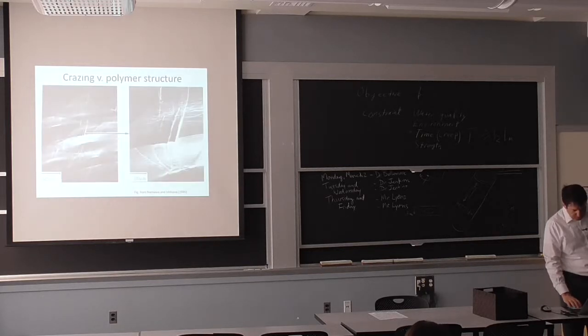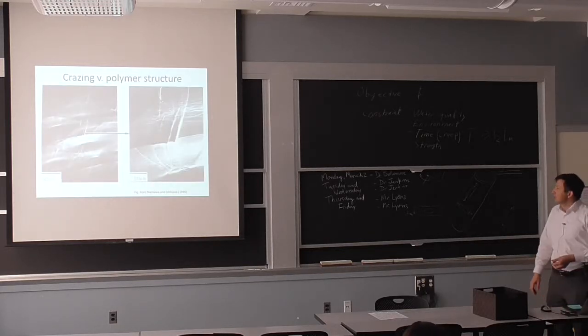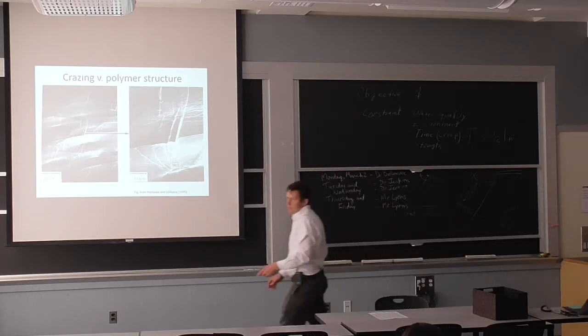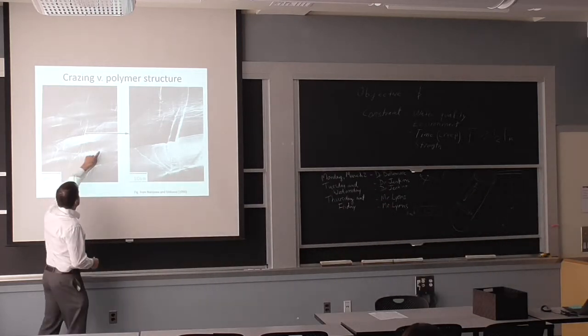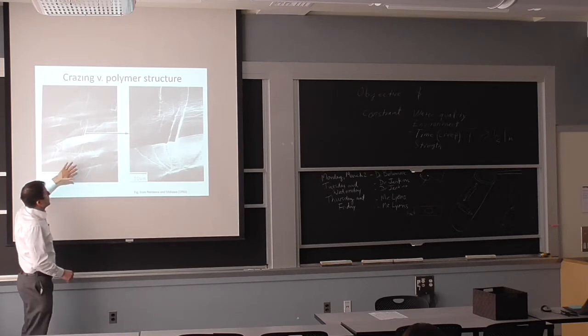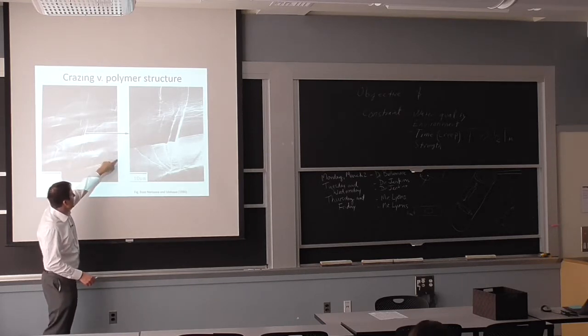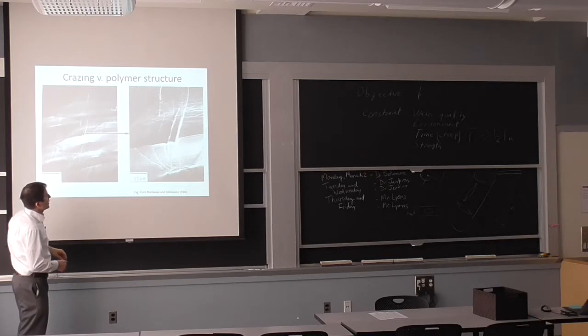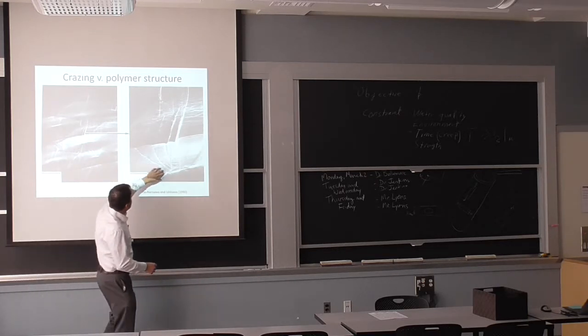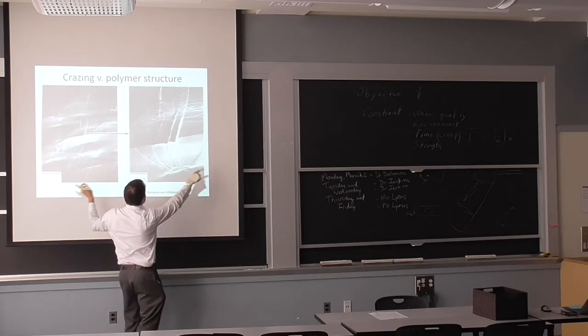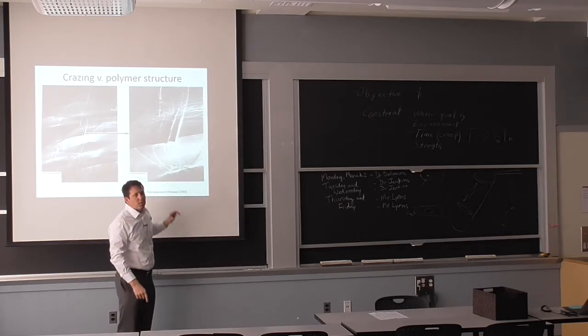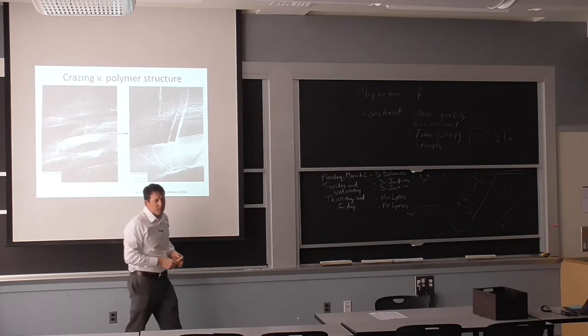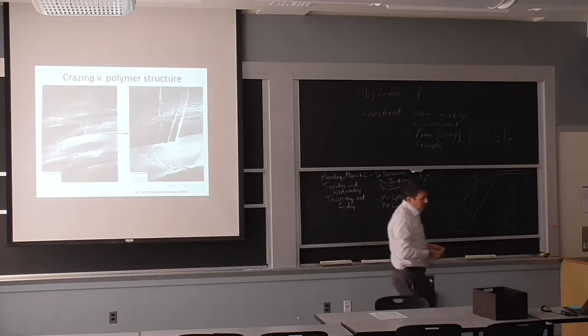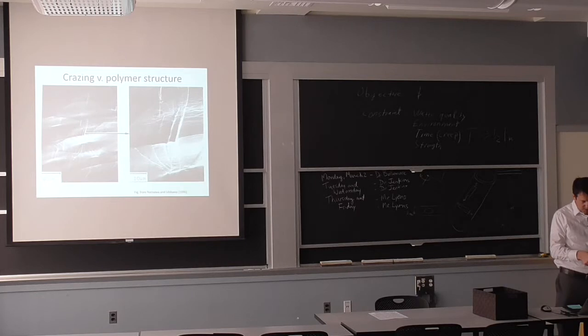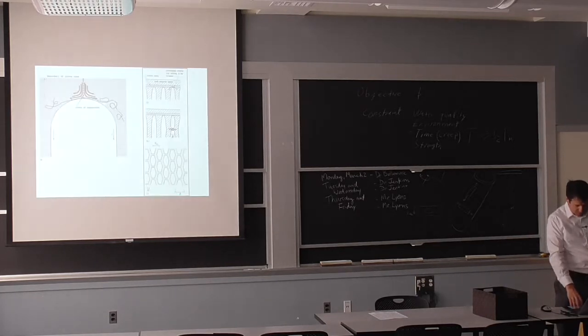This is a little bit how it can look on the surface of the sample. So you see this very light. It's not the best viewing here, but you see the surface. It's a surface, so we're not looking into the bulk, and that's why these edges may look a little more square than they really are. On the blow up here, you can see you're applying the stress in this direction, and it's starting to form the craze between those crystallites that we talked about at the beginning. So there's a lot of implication associated with the original structure here and forming the craze.